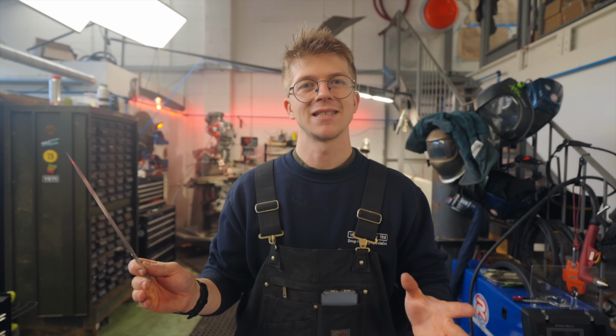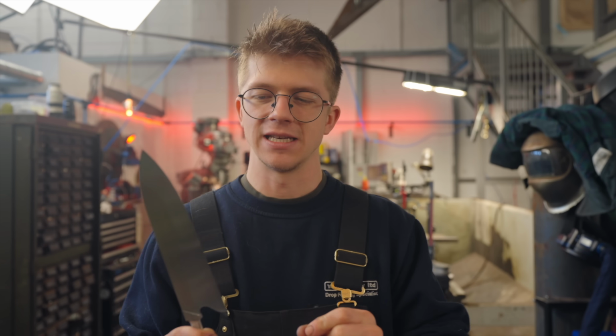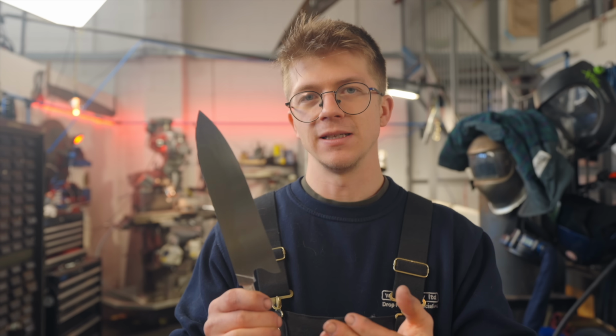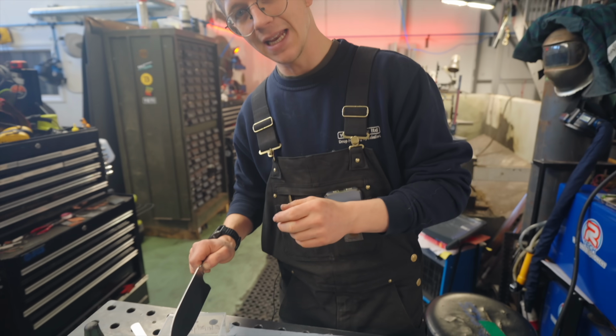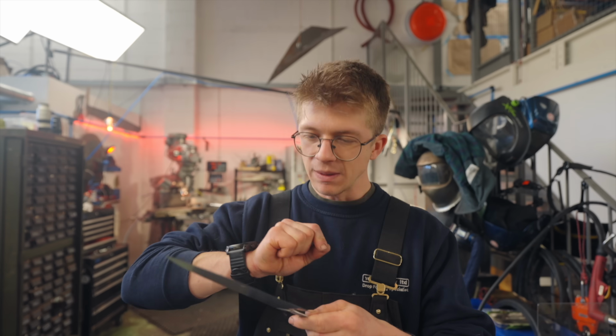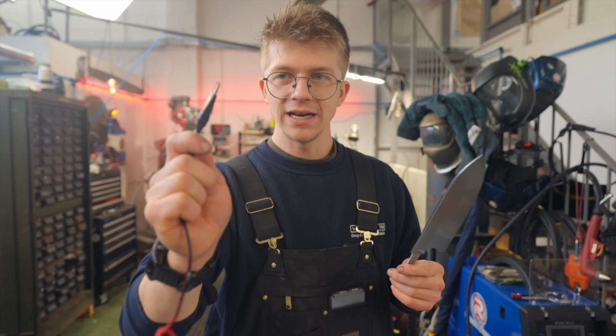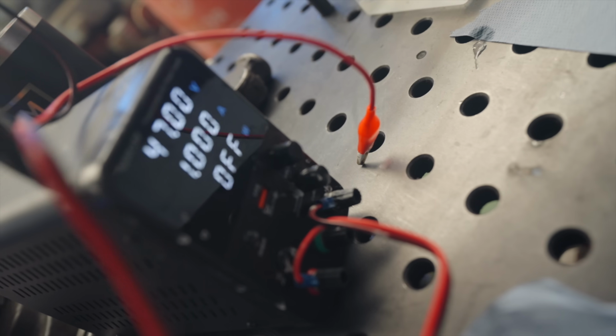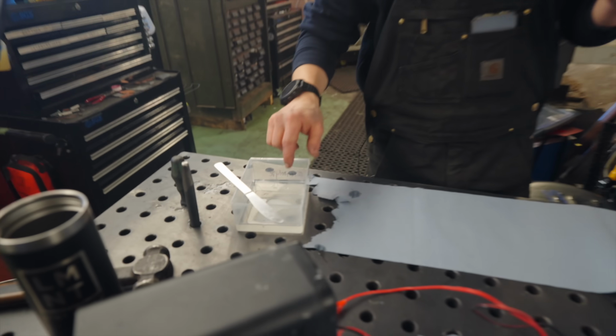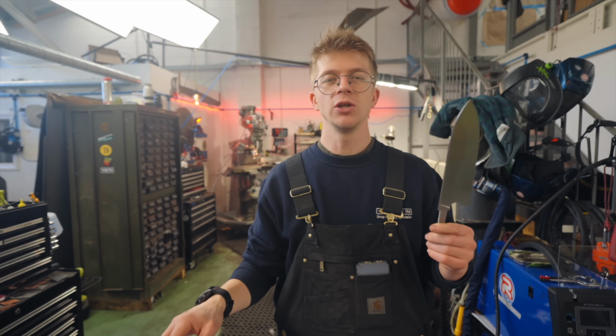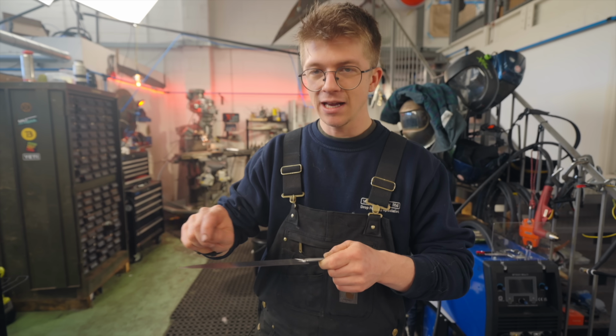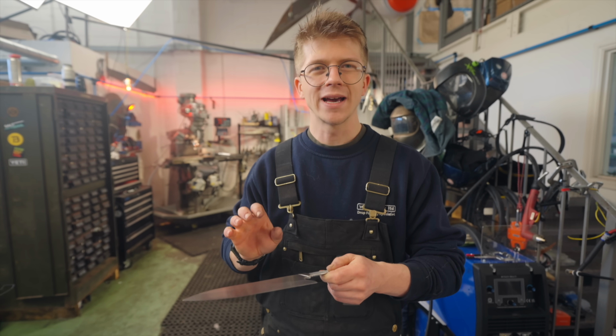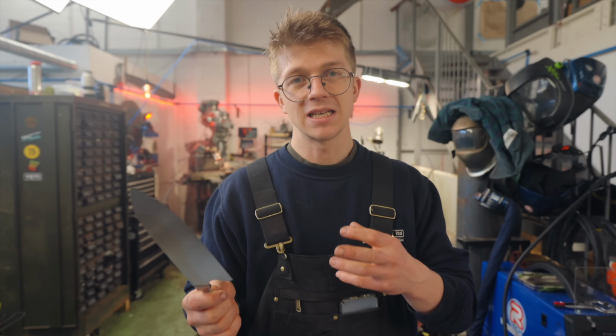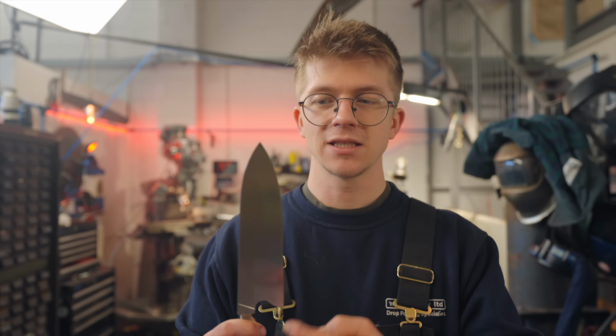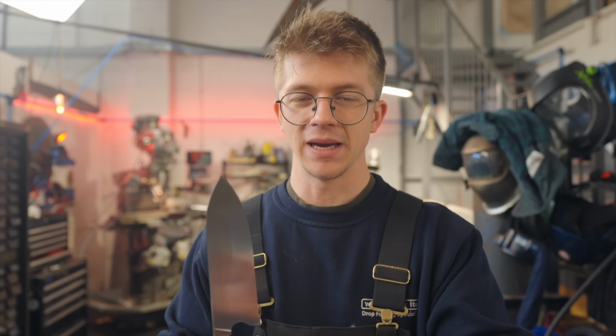Now, when we did our last sets of experiments, it didn't quite make it into the video, but the best results I got with the anodizing on our samples that also had a steel core were not when we dipped it in the electrolyte, but were when we painted it on by attaching one end of our DC power supply thing to a rag that was saturated in our electrolyte solution. And that was literally painting it on. The current, the electrolyte, working its magic to color the titanium because there seems to be a big problem anodizing titanium when steel is in the mix.